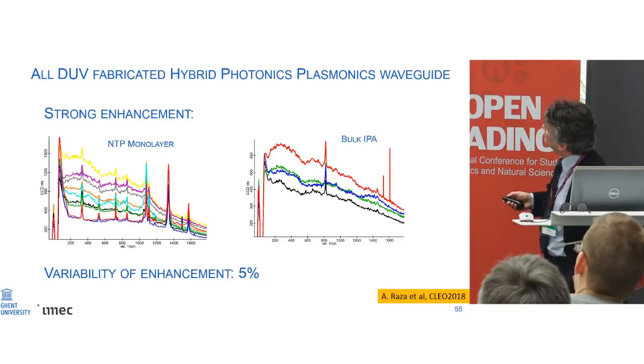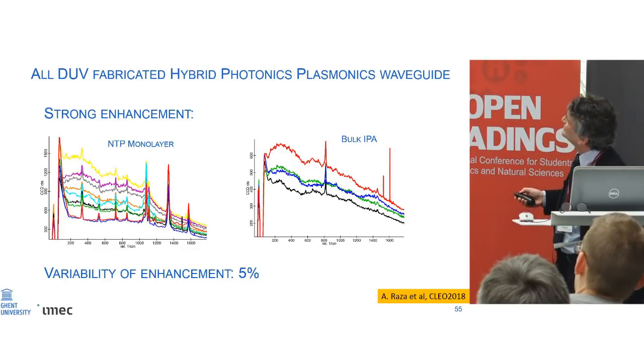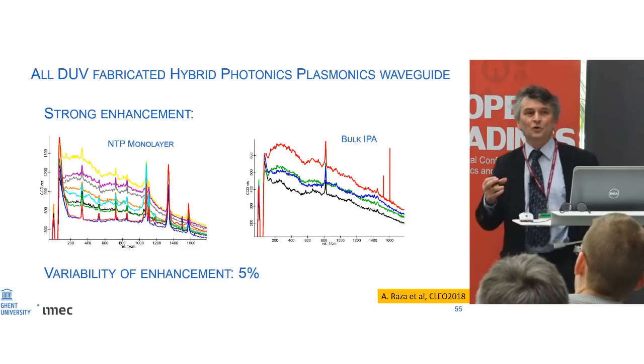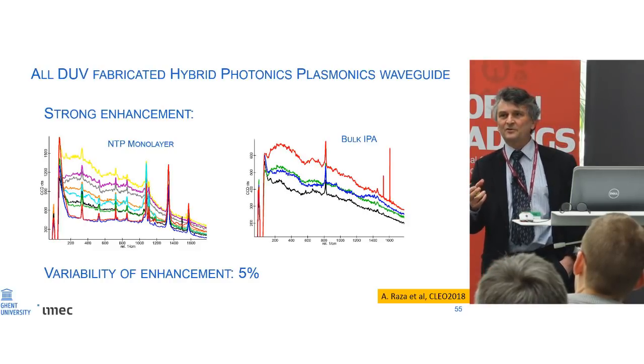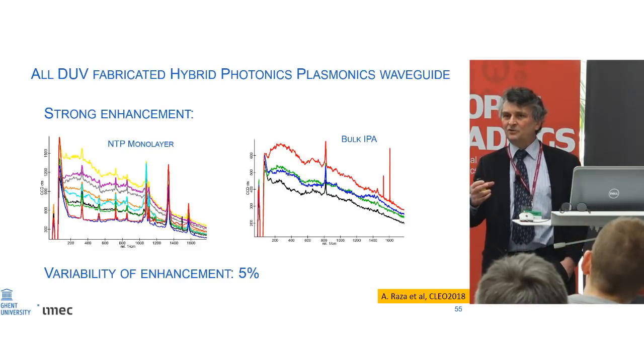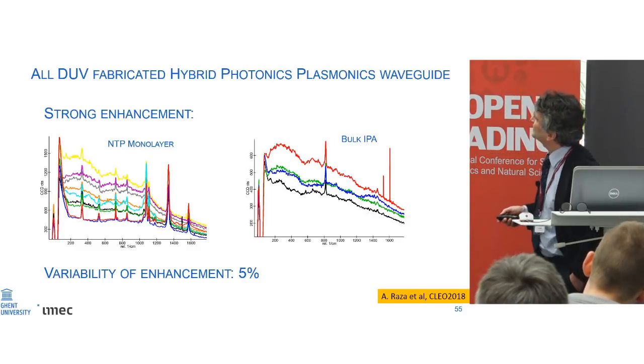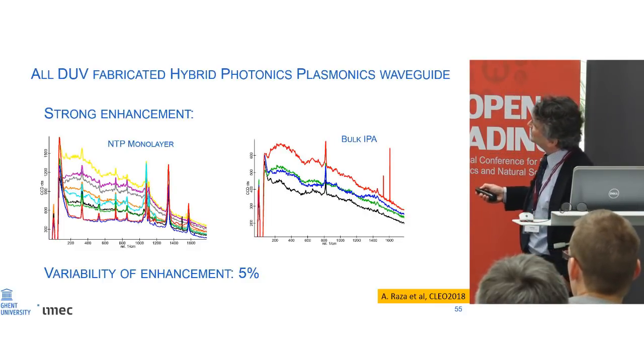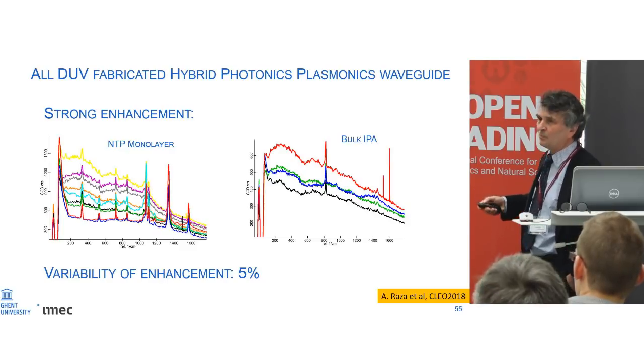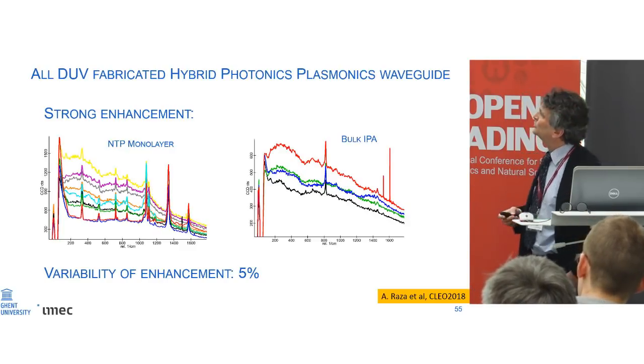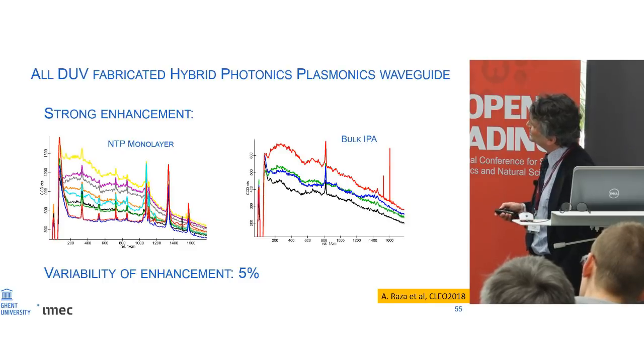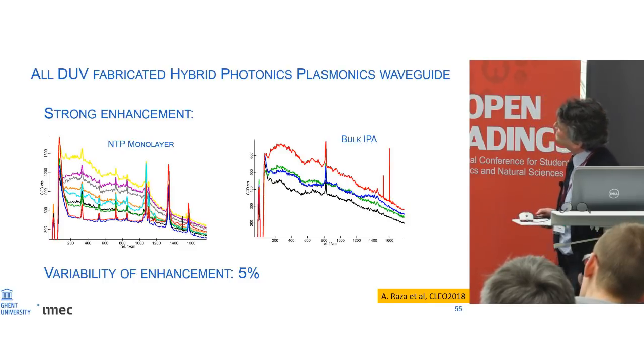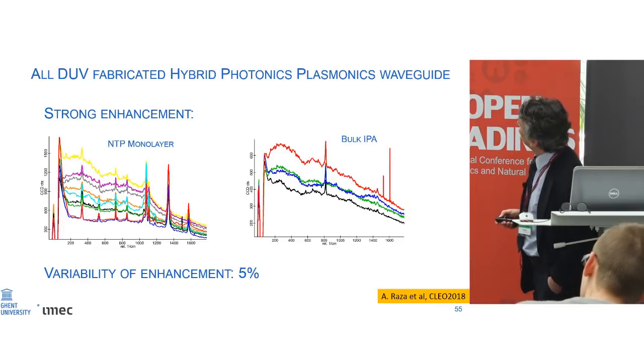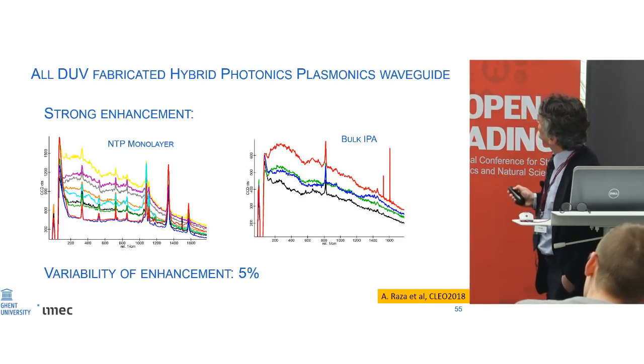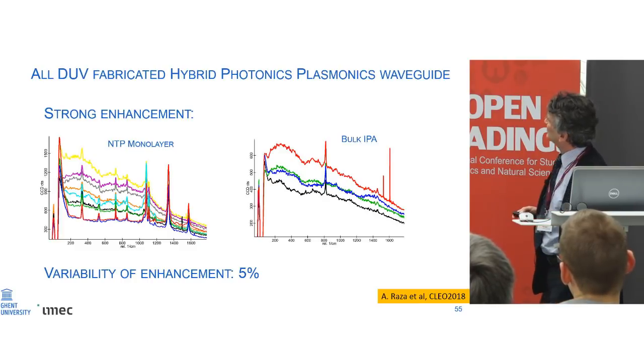And that works, and indeed we were quite astonished to be honest to see beautiful spectra from this approach. These structures are not long because the plasmonic structures are heavily absorbing, so they are perhaps 4-5 micrometers long. Longer doesn't make sense. But here you see Raman spectra of NTP. That's a molecule that is sulfur bound to the gold as a monolayer, and we see the most beautiful spectra that we have ever seen of NTP from this approach. Also, bulk liquids like this alcohol gives quite good spectra.